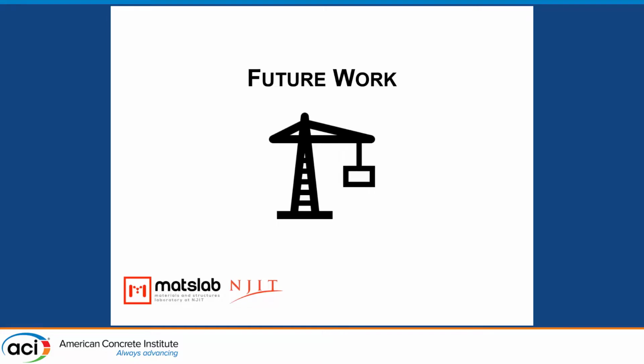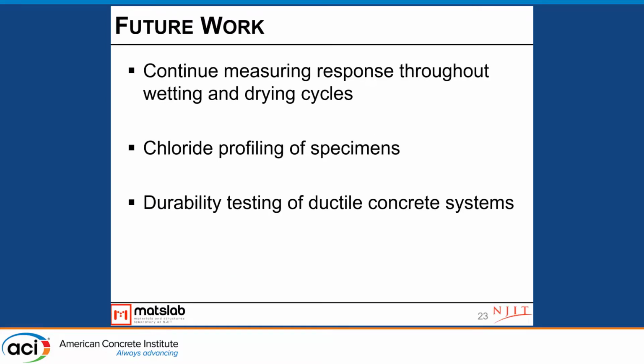As the future work in this project, we need to continue measuring response throughout wetting and drying cycles. We do wetting and drying cycles each week: 1 week of drying and 1 week of ponding. And also chloride profiling of a specimen. At the end, we need to make powder at different depths of concrete and see how much chloride we have at each depth. We also have other durability testing on this ductile concrete system, like freeze-thaw, salt scaling, and drying shrinkage. We cast the specimens and we are just measuring the results for these tests.